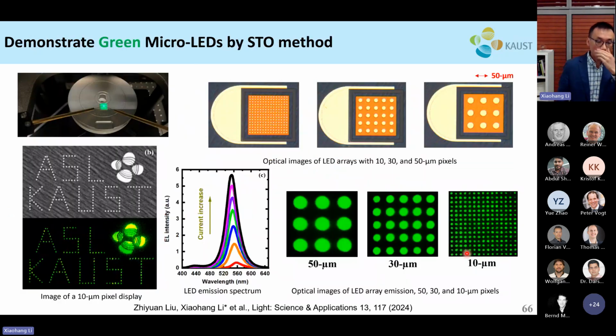And then we utilize this to fabricate the green micro LEDs. Okay, so basically this is a preliminary demonstration of the green LEDs with different pixel sizes, showing our lab name, KAUST, and also the logo of KAUST. So here I show different pixel sizes from 50 to 30 to 10 micrometer. In general, they have a relatively uniform distribution in terms of the light emission.